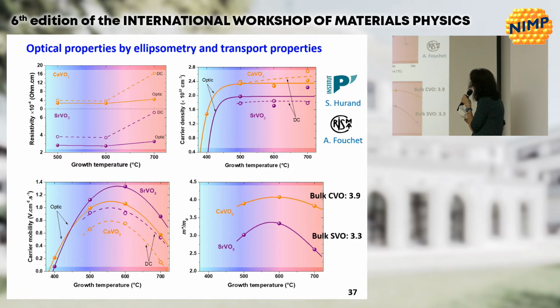Transport measurements were made, and also optical properties by ellipsometry. With these two techniques, it was possible to extract different parameters. The resistivity first, as you can see, is very low, up to 600 degrees Celsius. Then the carrier mobility was measured, and it is really high, also higher than for indium tin oxide. The carrier mobility follows a parabolic curve, with a maximum around 550 degrees for these materials. Finally, the effective masses were also extracted, and they are close to the bulk value.